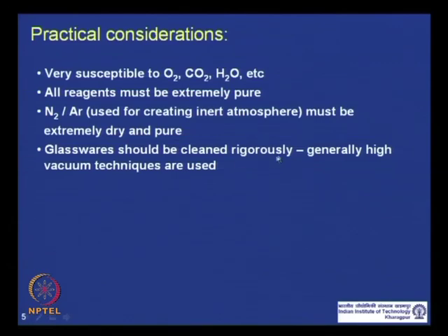And your glassware has to be clean. In practice, the scientists who carry out an anionic polymerization reaction flame dry, which means they heat the glassware under flame and then apply vacuum continuously. So, any oxygen, any moisture which was absorbed, or any impurities on the surface of the glassware, get cleaned up.